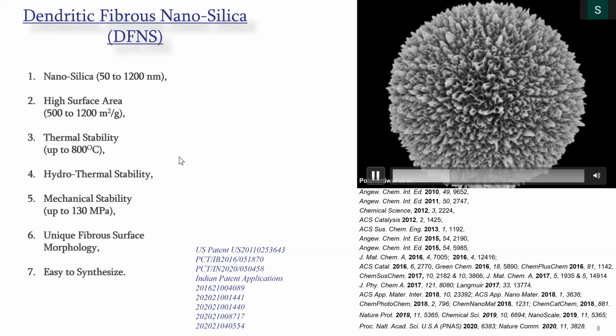Okay, so this is our material where we have a silica with nanoparticles from 50 to 1200 nanometer, high surface area of 500 to 1200 meters squared per gram, and excellent thermal stability and mechanical stability. So one can use this for high temperature and high pressure reactions. And most important thing, we haven't used any fancy technique. It's easy to make. If you go to this Nature Protocols, we have explained step by step every single step so that you can make it in your lab.